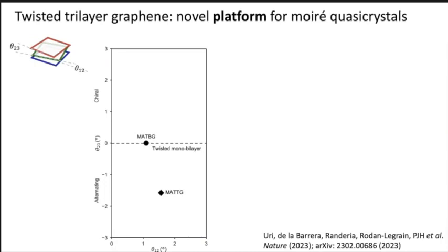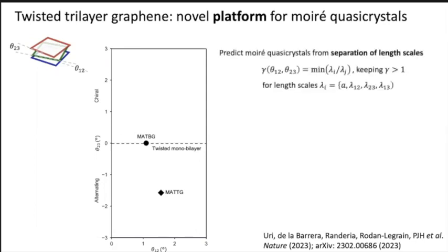Magic angle twisted trilayer graphene, the alternating one, has the same angle here and here, about 1.6 degrees. I mean, 1.6 and then minus 1.6, same angle, but alternating, opposite sign. Twisted monolayer-bilayer graphene, another correlated system, also only has one angle. In general, if you want to predict where Moiré quasi crystals are going to form, you have to look at the separation of length scales of the different lengths involved in the system, okay? So this parameter gamma is related to the minimum ratio of length scales in your system, while keeping this gamma greater than one, okay?